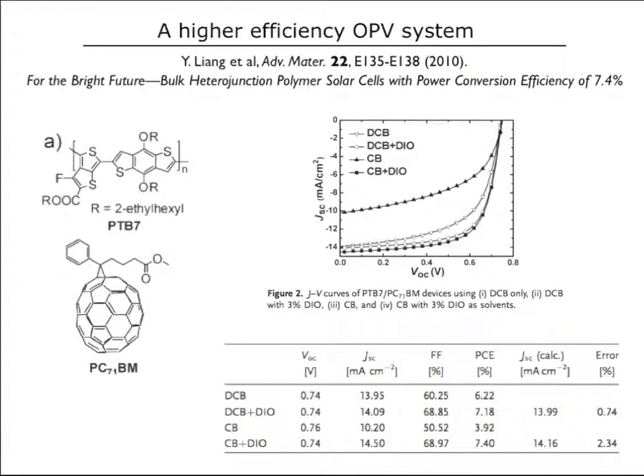So to give you an idea of device performance of a high efficiency but somewhat standard device, I cite Yang Yang's work from UCLA. He had published a 7.4% device based on PTB7 and a C70 derivative. And what he's done is tried different processing techniques, different solvents, and finding the ideal combination was able to get a 7.4% device. So typical numbers are current of about 14 milliamps per centimeter squared, open circuit voltage about 0.7, fill factor of 70%.